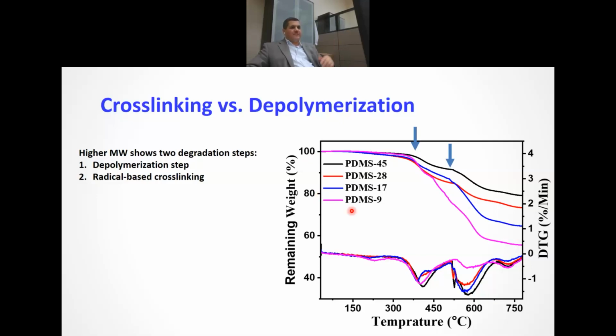The first thing, as you can see, is that there is a big difference between, for example, the very high molecular weight, which is the black curve. It has two degradation steps, as you can see. And the pink one, which is the lowest molecular weight, almost has one degradation step. And this is very, very important in terms of understanding the mechanism of degradation of these kinds of coatings when you apply the TGA test.